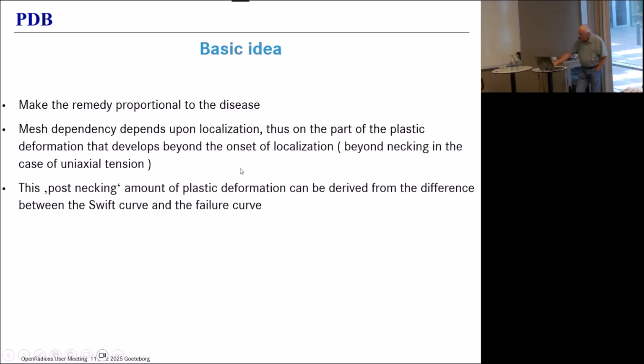Well, I finally come to what we did. So we somehow have to come up with a regularization that is triaxiality dependent. We can determine a regularization curve for uniaxial tension. We're not going to escape that. We will always have to do that. And we know that under pure shear, we don't have to regularize at all. But what do we do for other triaxialities?